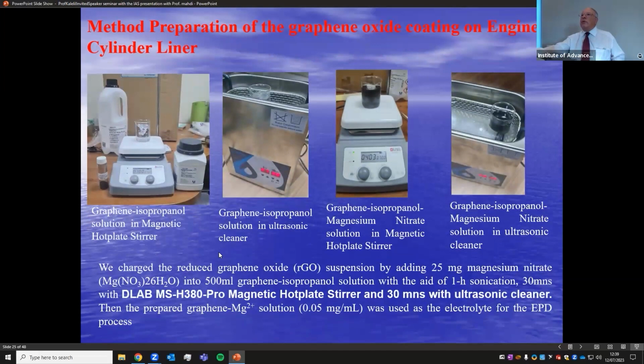First of all, we prepare the graphene with isopropanol solution. The duration on the magnetic hot plate stirrer and ultrasonic cleaner is 1 hour, 30 minutes, 30 minutes. It should be well dispersed, in colloidal form. Then we add the magnesium nitrate, with amounts according to the recipe from the literature survey. The graphene isopropanol mixture is mixed with magnesium nitrate here, still on the magnetic hot plate stirrer, and also in the ultrasonic cleaner.